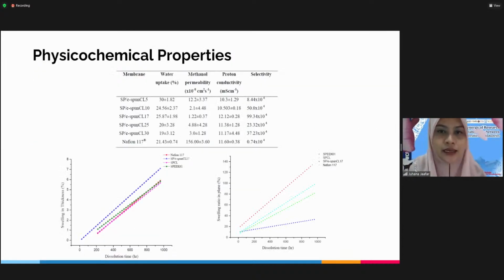Okay, and here are some of the results on the physicochemical properties such as water uptake, methanol permeability, and proton conductivity. From the methanol permeability and proton conductivity, we can compute the selectivity. The selectivity is proton conductivity over methanol permeability. Below shows the swelling results, in plane and in thickness swelling. It is a very interesting result from this finding.